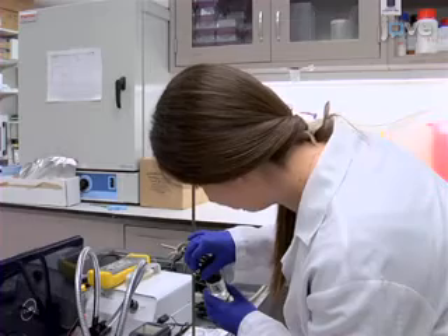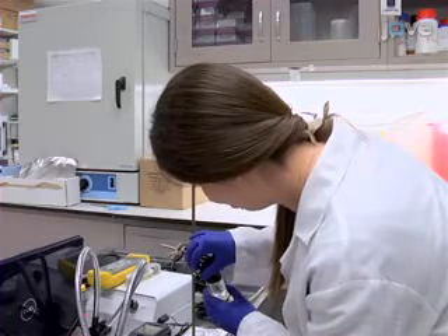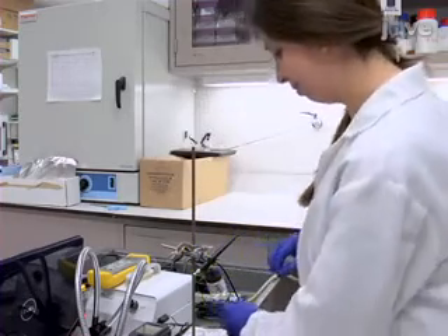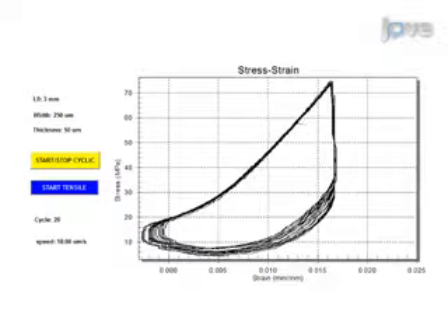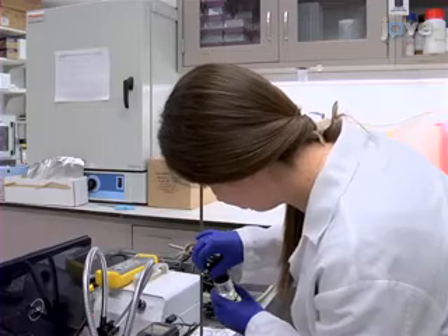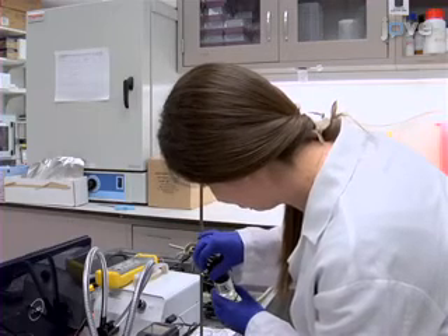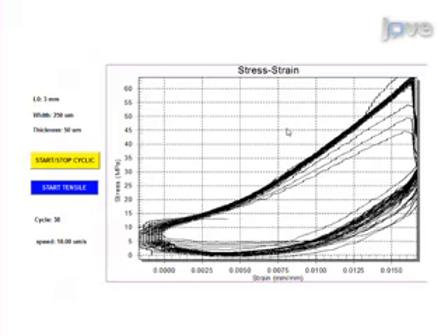To determine the desired humidity conditions, gradually increase the flow from the airbrush nozzle and monitor the slope of the stress-strain plot as a function of the amount of flow from the airbrush. The maximum flow that does not cause a significant reduction in Young's modulus over a period of 60 seconds is the level that will be used for the ex vivo experiments.